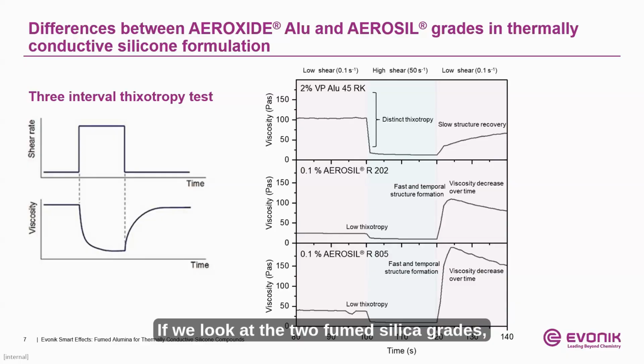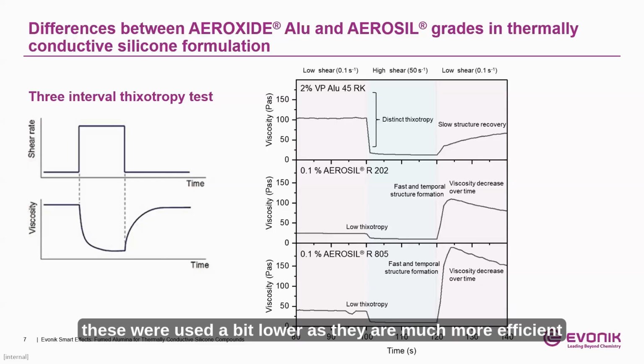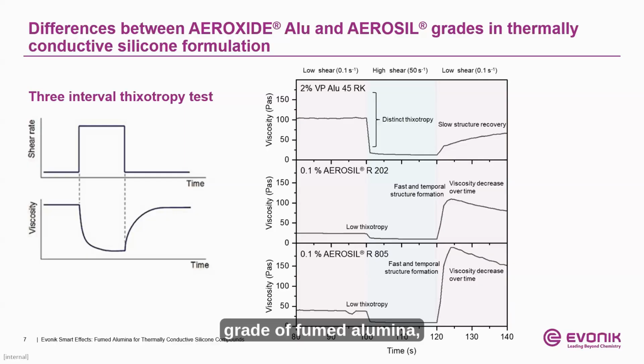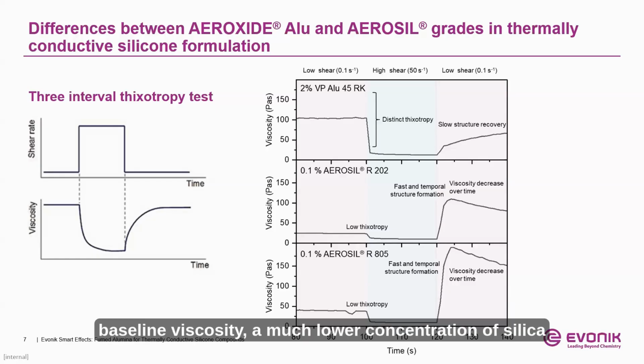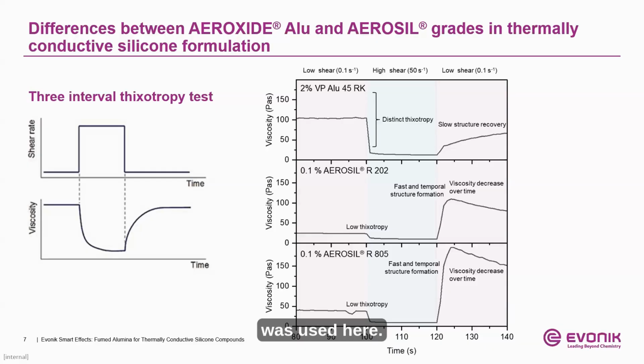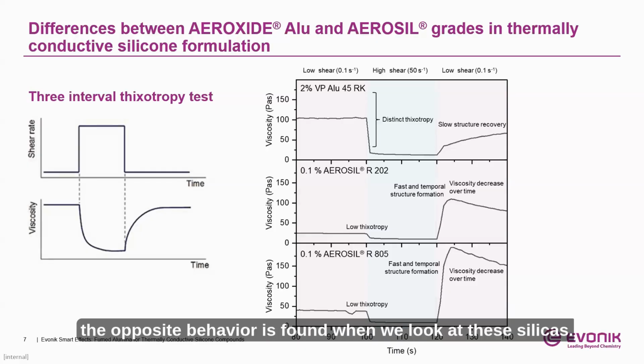If we look at the two fumed silica grades below, the Aerosil R202 and the Aerosil R805, both used at 0.1%. Again, these were used a bit lower as they are much more efficient at thickening in these systems than this particular grade of fumed alumina. So to generally keep a relatively similar baseline viscosity, a much lower concentration of silica was used here. But essentially the opposite behavior is found when we look at these silicas.